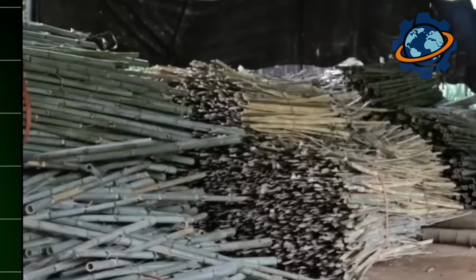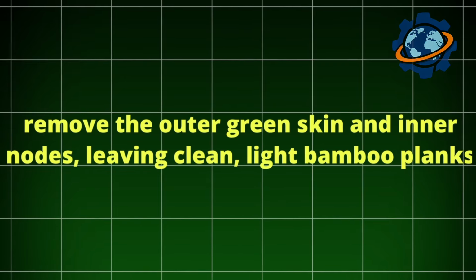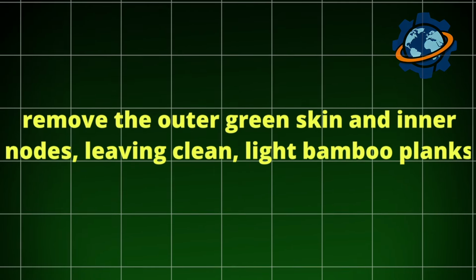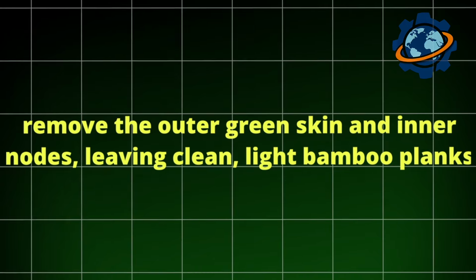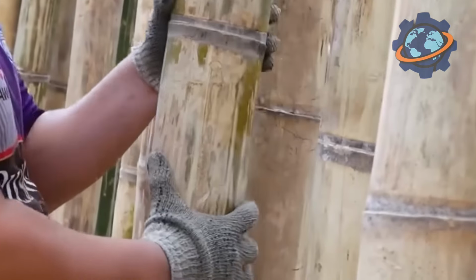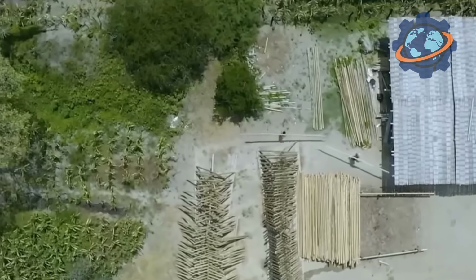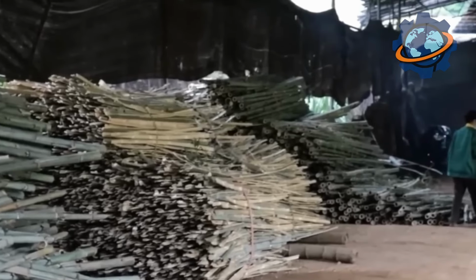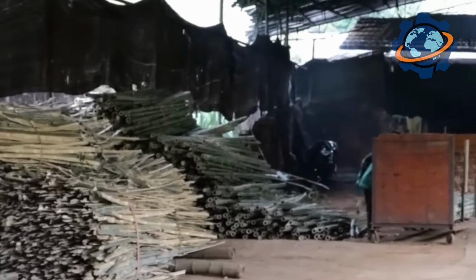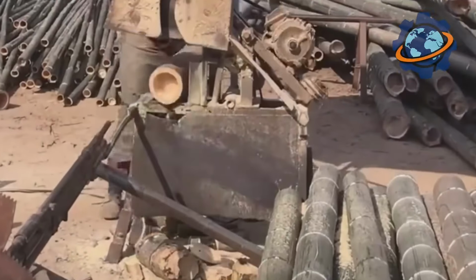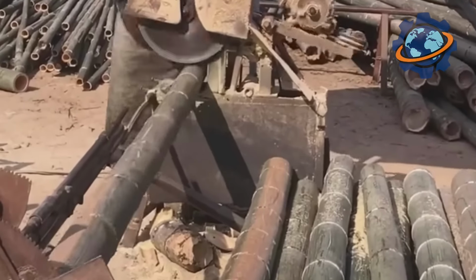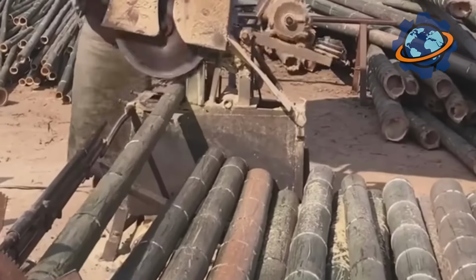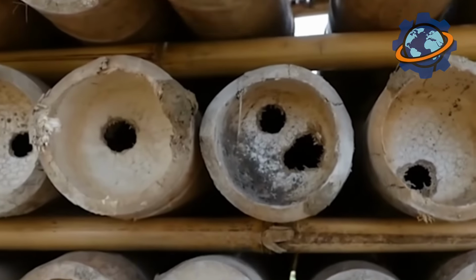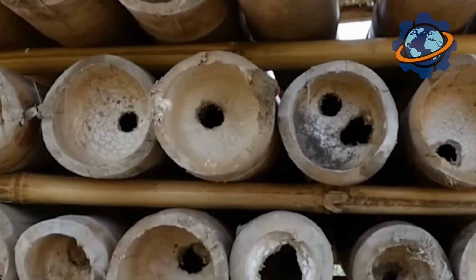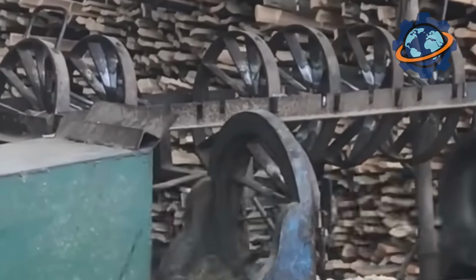The next step is to remove the outer green skin and inner nodes, leaving clean, light bamboo planks. But inside these planks still lurks an enemy of durability: starch and sugar, which are a favorite food for insects and mold. To get rid of them, the planks are submerged in huge vats of boiling water, or a hydrogen peroxide solution for several hours. This hot bath not only sterilizes the bamboo, but also washes out all the nutrients.